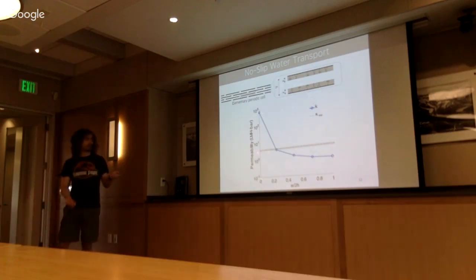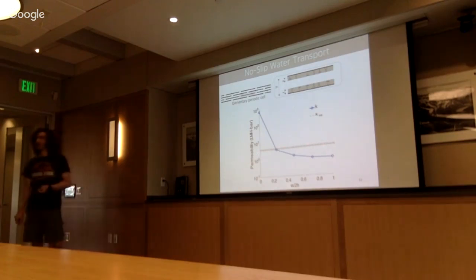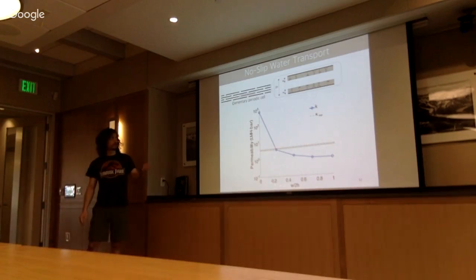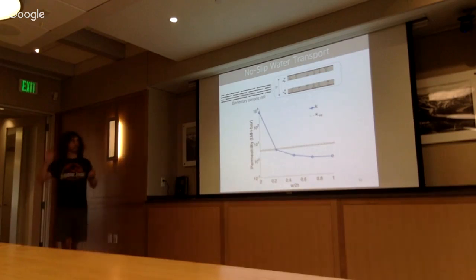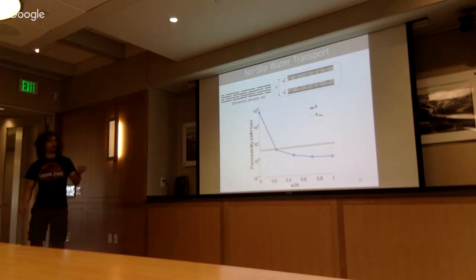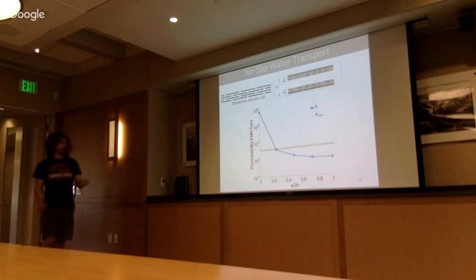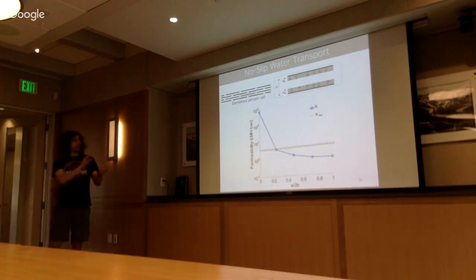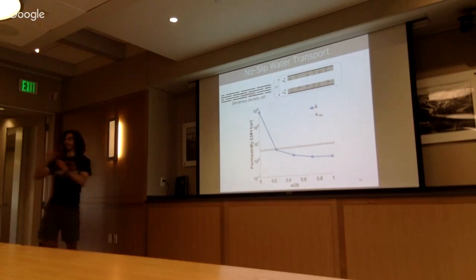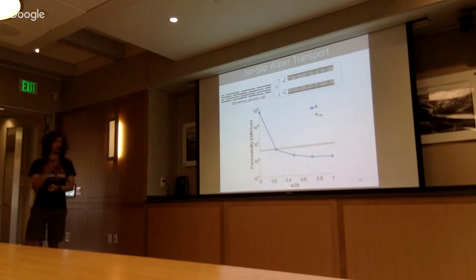This, though, is really off compared to experimental results, which are this dashed line. So by putting W equal to 0, we're in the frictionless scenario, and we're really off from experimental results. But when we put W equal to 0.2, that means W is 20% of the separation distance. If the separation distance is 1 nanometer, W will be 0.2 nanometer. We have a really good match with experimental results. And this is really good because 0.2 nanometer is exactly the extent of hydroxide and epoxide functionalities. So there is a good match between theoretical and experimental results.